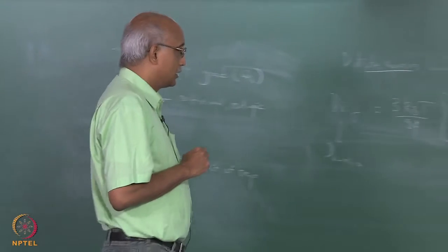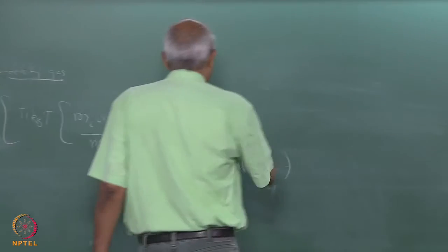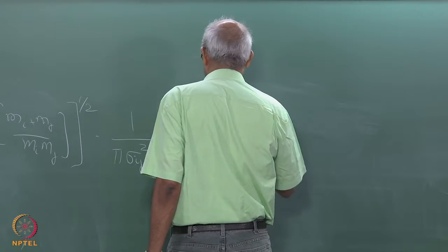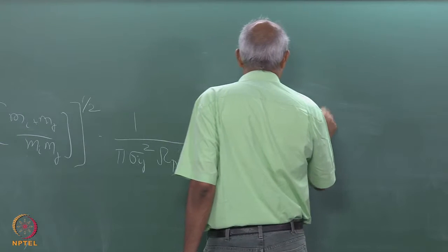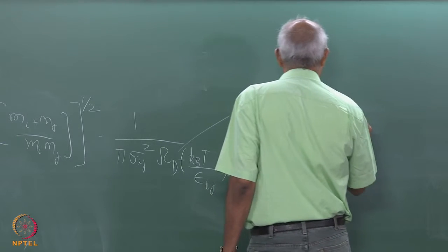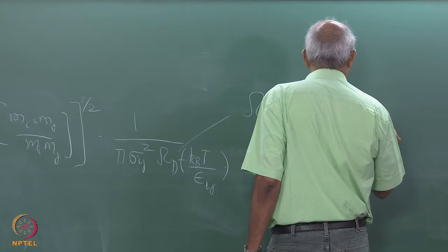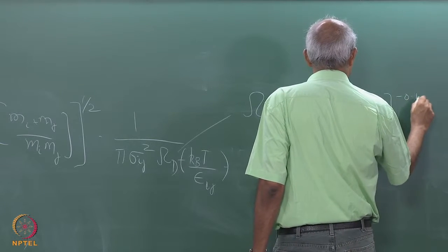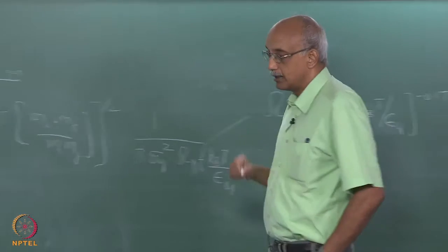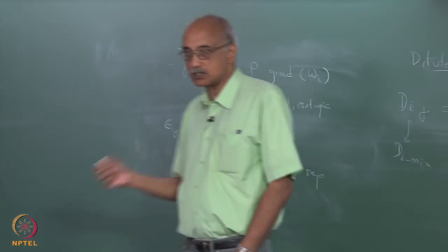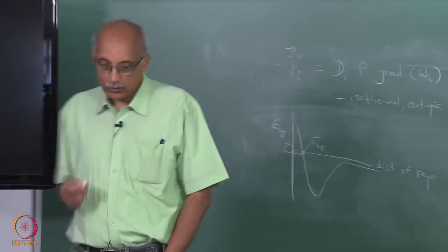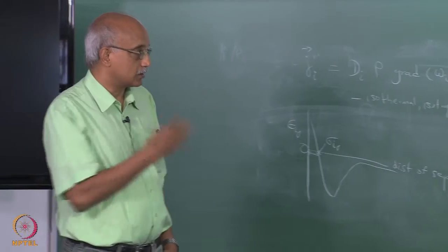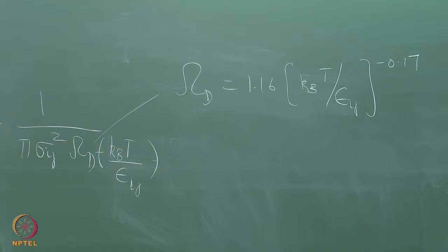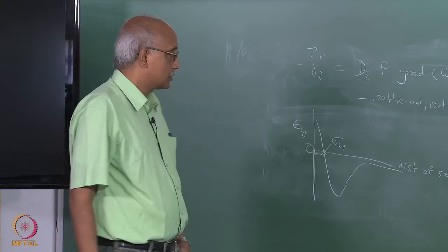And again this omega d parameter is written as 1.16 times kBT by epsilon ij to the power minus 1.7, and again it corrects for the fact that the diffusing molecules are not hard spheres. The closer they are to a hard sphere condition, the closer omega d will be to 1, but in general you have to include this correction factor.